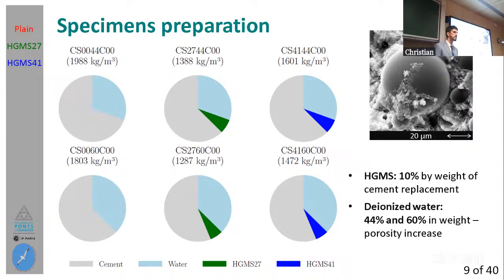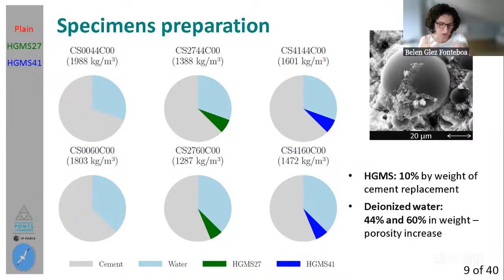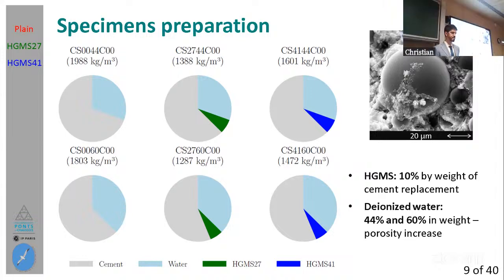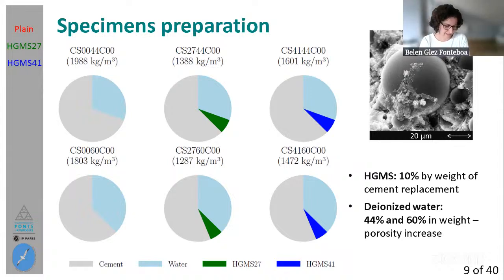Yes, I agree. Okay. In this regard, I would also like to suggest that a replacement by volume instead of by weight would have been better to discuss the results, because as you have said, you are replacing by weight, and it seems the same quantity, but as they have very different density, the quantity is very different in the mixes. In the slide that you are showing, you have represented the same volume, and it is not, because you are replacing by weight, so the volume is really different. Yeah. Anyway, it is okay.